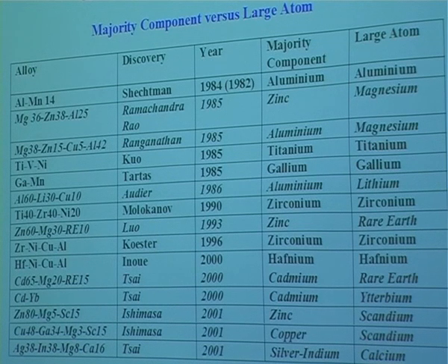But what I want to say is, having looked at it, we try to work on this, that the general tendency of metallurgical theory would be to look at the majority component, because you have a base, to that you add other components and you look at it. But we felt in these quasicrystals, where size plays an important role, you have to look at what is the largest atom. So what I have given here is the largest atom. If you look at them, it falls into a few classes. For example, aluminum and gallium, which will belong to the same thing, and titanium, zirconium, hafnium, which will belong to the same thing, and rare earth, ytterbium, scandium will come to the same size, and of course magnesium.